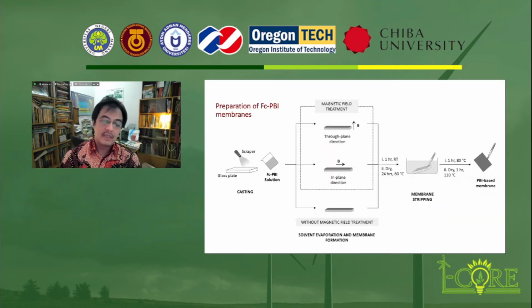This slide shows the fluorescein functionalized polybenzimidazole membrane preparation. The membrane was cast with the fluorescein carboxylic acid solution. The solution was poured onto the glass plate and cast with a stainless steel scraper, and a magnetic field was applied perpendicular, meaning through-plane direction and also in-plane direction, to the plate with a strength of 0.3 Tesla at room temperature.